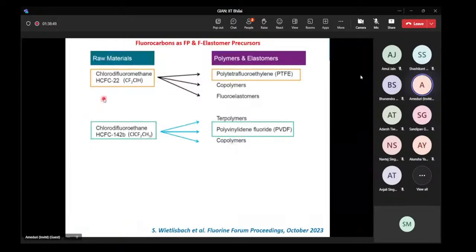So PTFE can be prepared from HCFC-22. VDF can be prepared from HCFC-142b. I don't insist on these figures, but this is the number of carbon, the number of fluorine: -2, -1. What is important is that from this derivative, by dehydrochlorination, it's possible to make VDF and then to make some PVDF or copolymers of VDF with, as I mentioned before, HFP, PMV, etc.